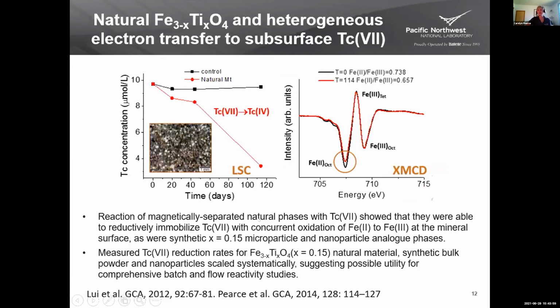And then we can go back, having conducted that study and demonstrated the importance of the iron 2-3 ratio in the bulk. We can go back and predict whether our material from the site would be able to do that reduction and monitor that over a longer period of time. And again, demonstrate that it's that solid phase iron 2 that's conducting the redox reaction with pertechnetate and reducing it to the insoluble Tc 4+ oxidation state, TcO2.